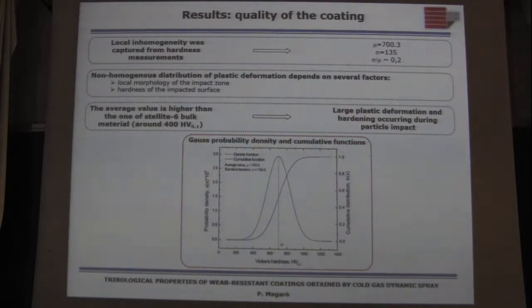On the microscale, the characterization was carried out by micro-hardness measurement on the top surface, and we reached a mean value of 700 Vickers, but a very high coefficient of variation around 0.2 was also obtained. This can be attributed to the different path of each particle from the gun nozzle to the impacted surface. Moreover, the local morphology of the impacted zone, the different hardness of the impacted zone, can influence the results of the coatings.